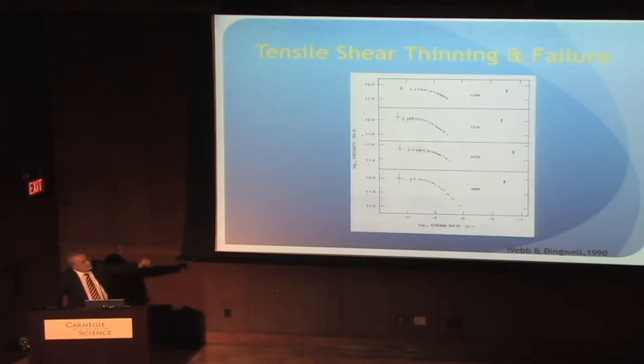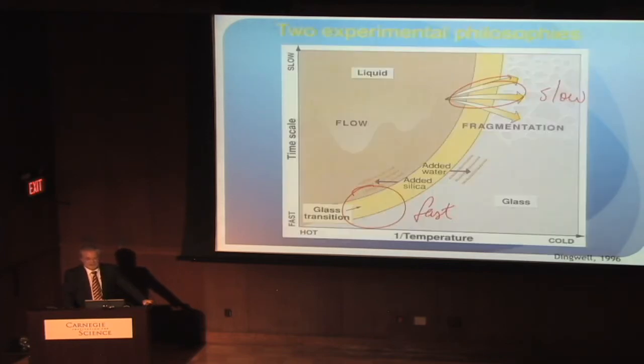And if you go to the glass transition, the following happens. You see in the upper left-hand portion of each of these curves a flat plateau. As you go to the right, something very scary happens for a rheologist who's trying to keep his materials under control in the lab. You hit this cliff and you just dive off the cliff. The resistance to flow disappears under your feet, so to speak. It's a runaway process in most kinds of rheological measurements. And so this is the onset of non-Newtonian viscosity, to put it in a very gentle way. It's actually shear thinning. And in each of these experiments, the last data point on the right was terminated by a snapping of the liquid. So brittle behavior of what was, nominally speaking, a liquid. And that's what happens when glass is brought to the glass transition.